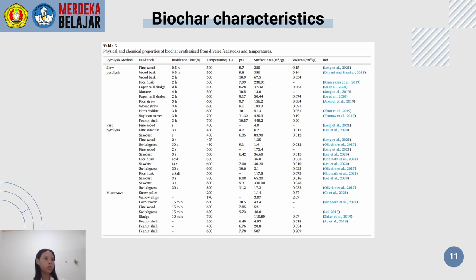The O/C molar ratio is significant for identifying and distinguishing biochar from other carbonization products. O/C values greater than 0.4 imply that biochar is less stable. The molar ratios of H/C and O/C in lignocellulosic biomass are about 1.5 and 0.7, respectively. Pyrolysis results in devolatilization of biomass and enrichment of the solid fraction with carbon.